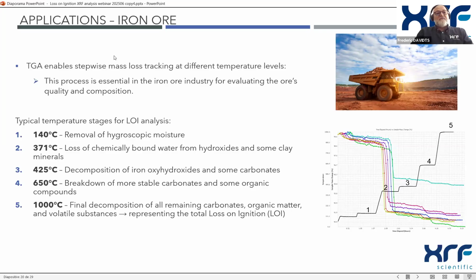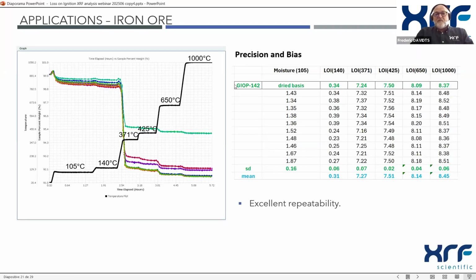Now the case of iron ore, sorry. Again, the TGA is also used to evaluate the ore's quality and the composition. And of course, there is a norm for that, which says that we need to determine the loss at 5 different temperatures, and it corresponds to the loss of different decomposition of different parts of the ores up to 1000 degrees, where we have the last loss of ignition part. So we can see here the sequential step of heating.